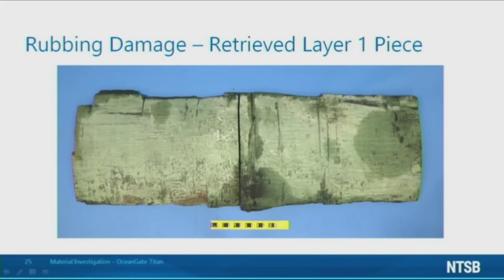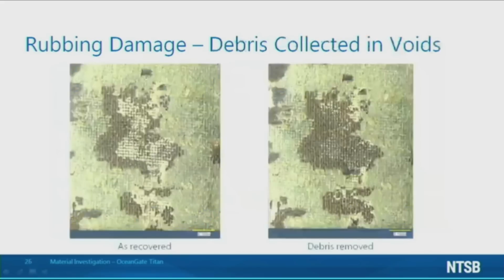Examination of the retrieved single-layer hull piece also revealed features that were consistent with rubbing damage on the adhesive surface. Voids were observed on the surface of the piece, like those observed on the trimmed end. As shown in the images above, some of these voids contained cream-colored debris that was readily removed with the tip of a fine blade and a synthetic bristle brush.